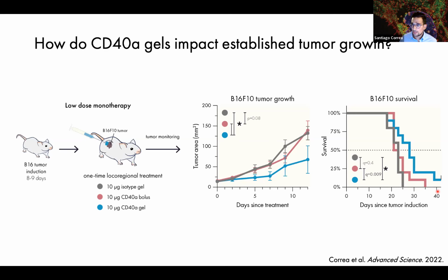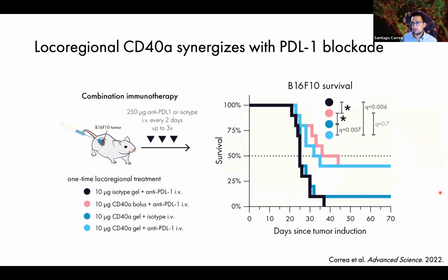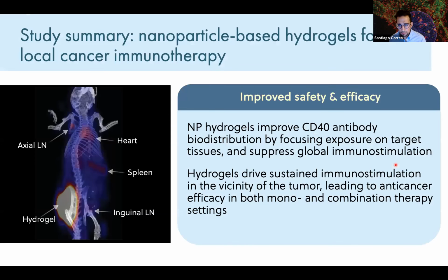I mentioned before that we are also quite interested in how this could be used in combination immunotherapy. And so we also looked at how efficacy would change when we combine this with frontline immune checkpoint blockade, PD-L1. And we were really excited to see that when we combine local regional approaches with immune checkpoint blockade, we go up to 40% long-term survivors, indicating a really synergistic outcome. Overall, we saw similar results with the local bolus and hydrogel here in this combination setting. But remember that the hydrogel also provided significant safety benefits that we didn't see with the local bolus administration route. And so overall, we were really enthusiastic about this technology as a drug agnostic way to locally administer potent immunostimulatory drugs.